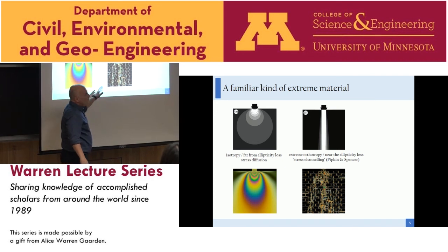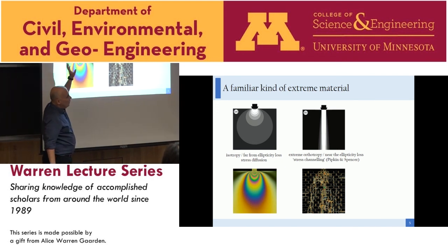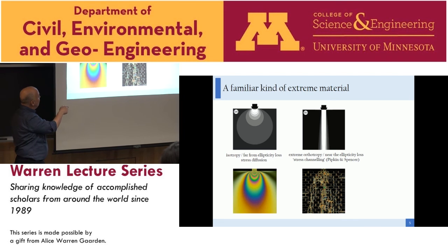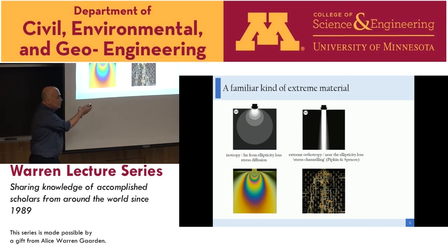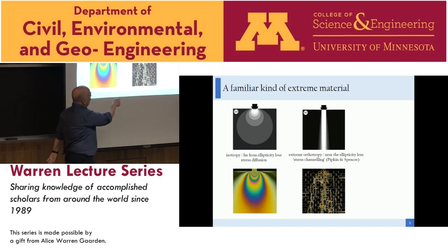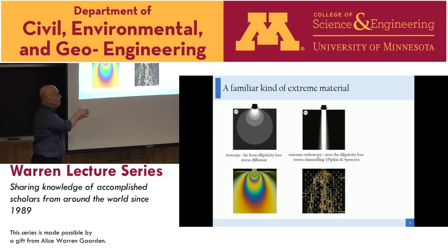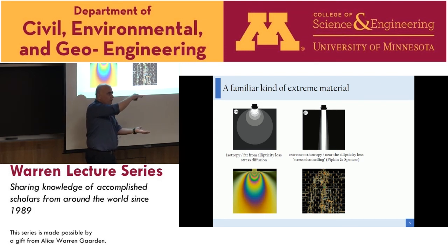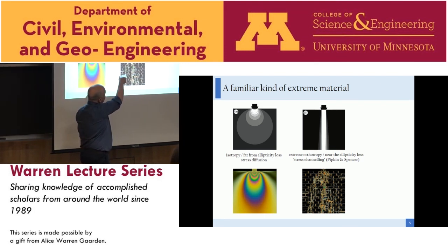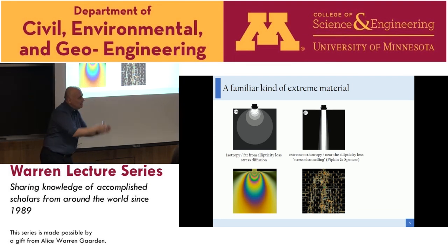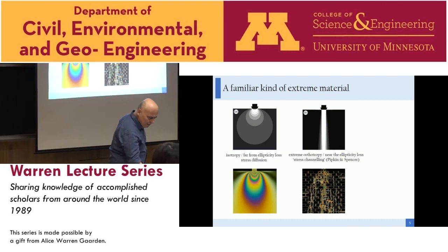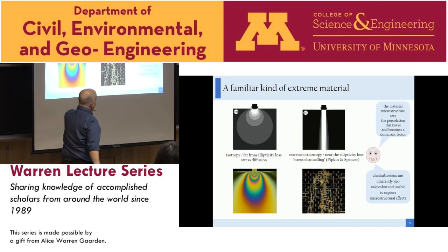A simple model of this is shown: on the left, a piece of isotropic homogeneous elastic material loaded vertically shows normal stress diffusion. On the right, following the idea of Pipkin and Spencer, a highly anisotropic material — weak in shear and stiff for compression — causes stress to channel almost vertically. This is reproduced by the experiment. Our interest here is to model the microstructure.